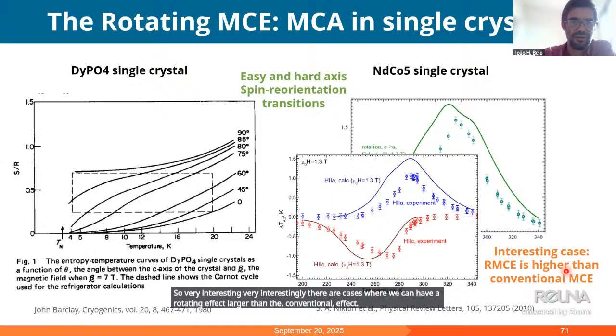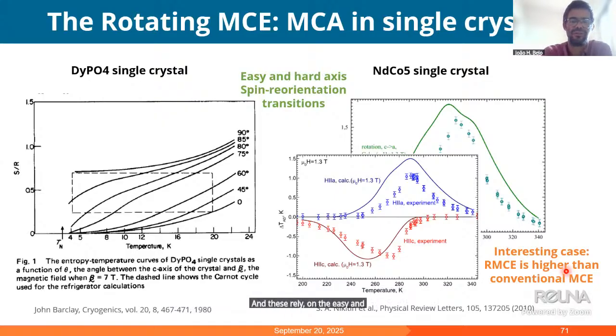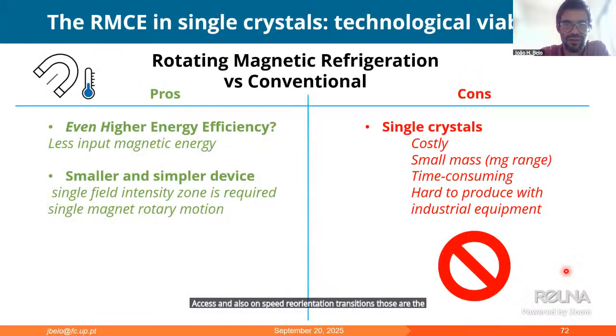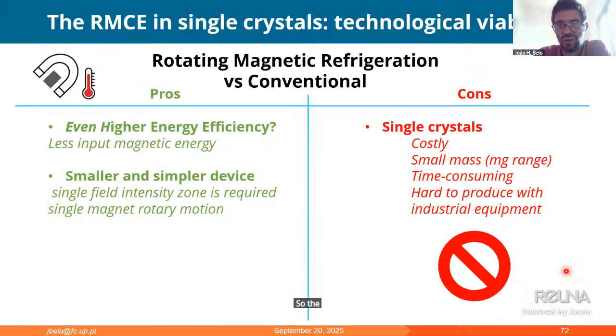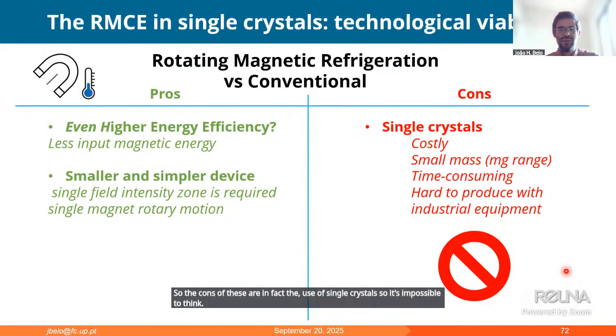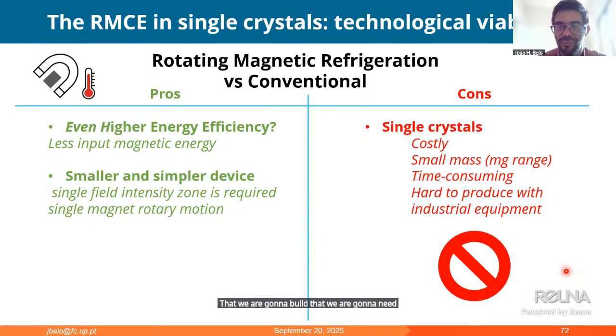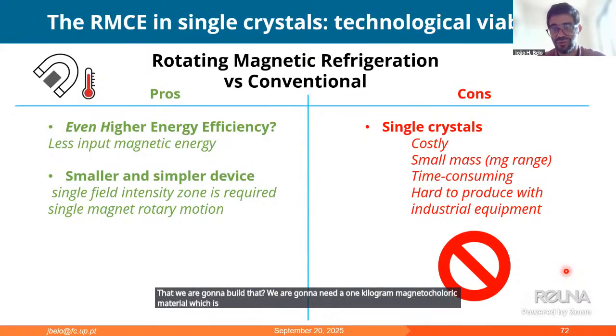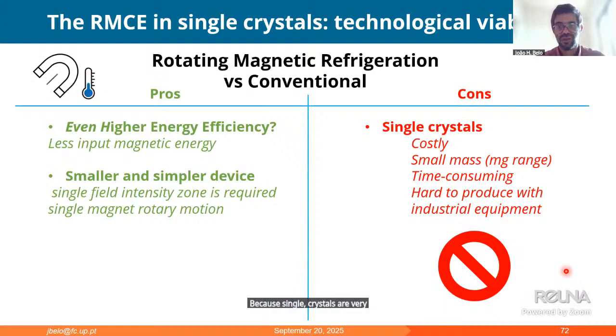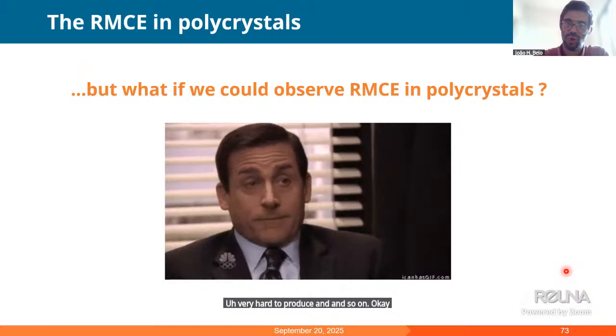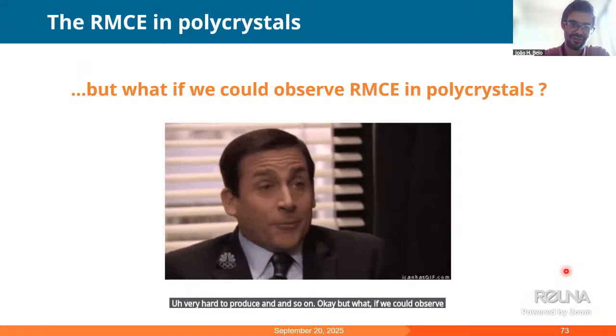These rely on the easy and hard magnetization axes, and also on spin reorientation transitions. Those are the physical phenomena behind it. The cons of this are, in fact, the use of single crystals. It's impossible to think that we are going to need 1 kilogram of magnetocaloric material that is a single crystal, because single crystals are very costly. They typically have small masses, are very hard to produce, and so on. But what if we could observe a rotating effect in polycrystals?